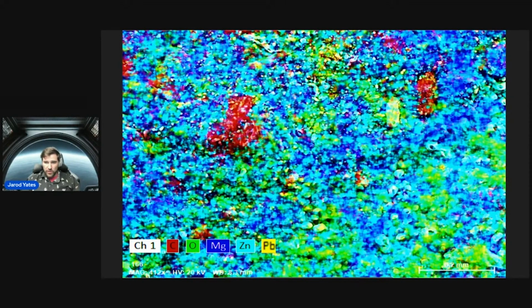So the yellow, that's the lead. The Oak Ridge National Lab report said this thing has about similar parts lead to bismuth, and stopped there and said, so it must be slag. I strongly contest that you should just stop questioning this because you detected lead in it. And here's why. We can see these microspheres, right? So you see a very thin layer of this turquoise zinc on these guys, and then you see the yellow lead peeking out of the ends there.